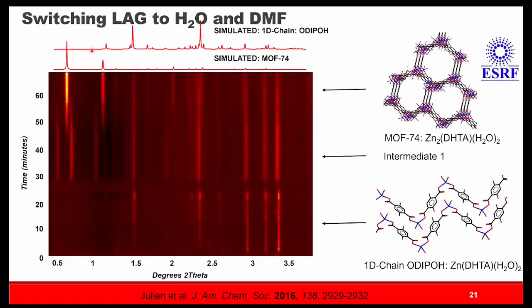One thing that I think is really important to note, and this we found was actually really interesting, if we switch this liquid-assisted grinding phase all of a sudden to 20% water and 80% DMF, we actually see that the reaction slows down quite a bit, but we're also now seeing the formation of an intermediate phase, which we have not been able to identify. So again, we start a reaction here, we finish the reaction here, we see the same 1D chain polymer where only the carboxylates have reacted with the zinc, but now we have this unknown intermediate phase, which unfortunately we weren't able to get the structure of, which then subsequently converts to the final MOF-74 structure.